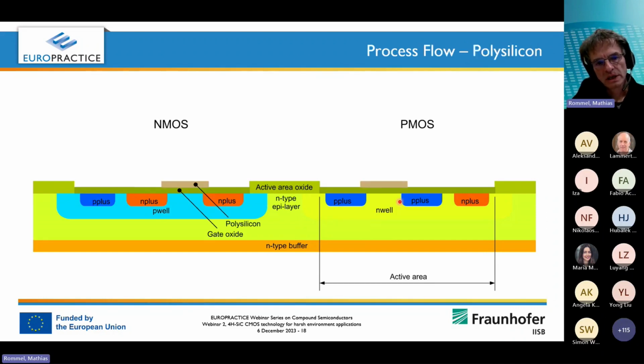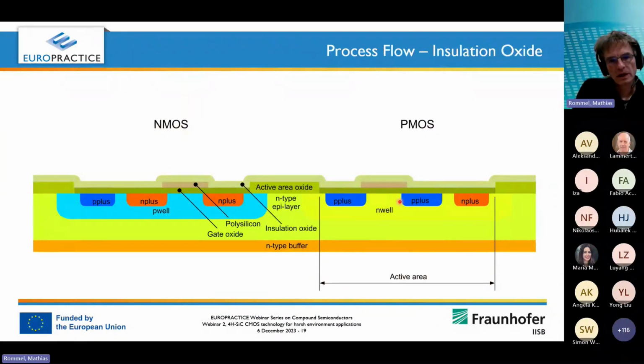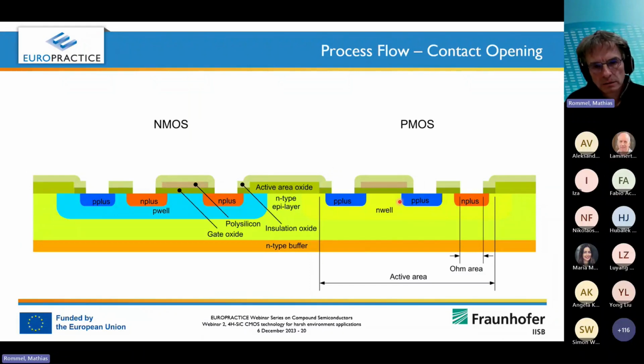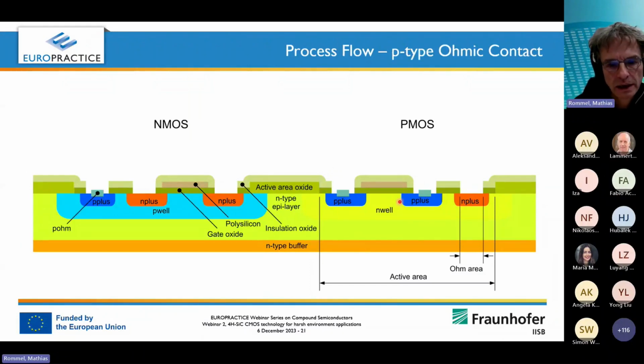We deposit the polysilicon, which we use as a gate electrode. It's a highly doped, typically a highly n-doped polysilicon. We cover this with an insulation oxide and then open the contacts. And that's also specific to silicon carbide, at least for our process. We use different ohmic contacts for P and for N-type layers. And we start here in this case with a P-type metallization, which later on will be annealed and forms then the ohmic contact.